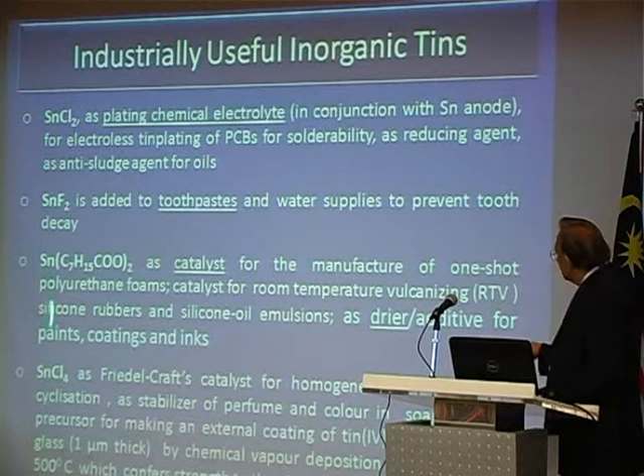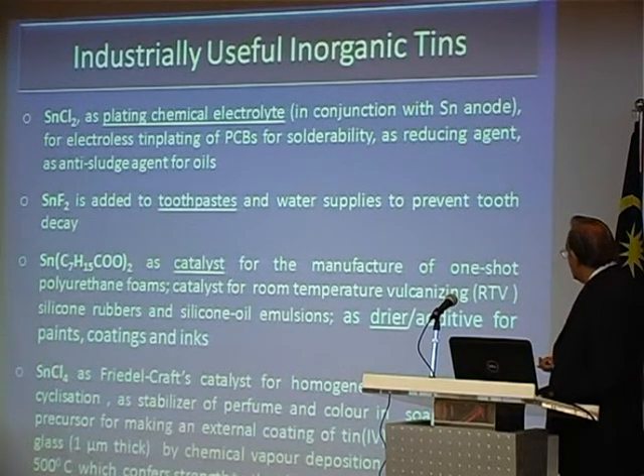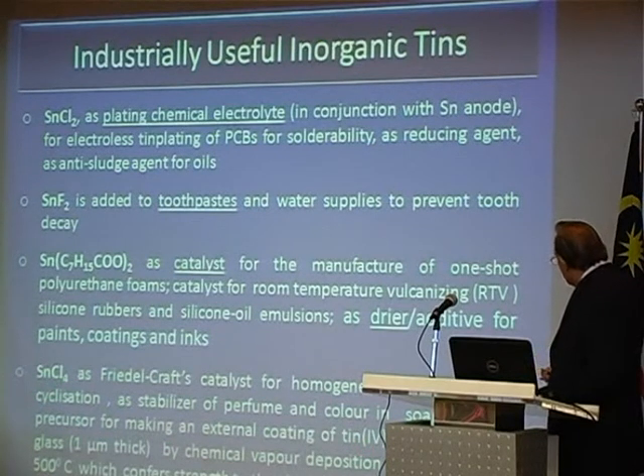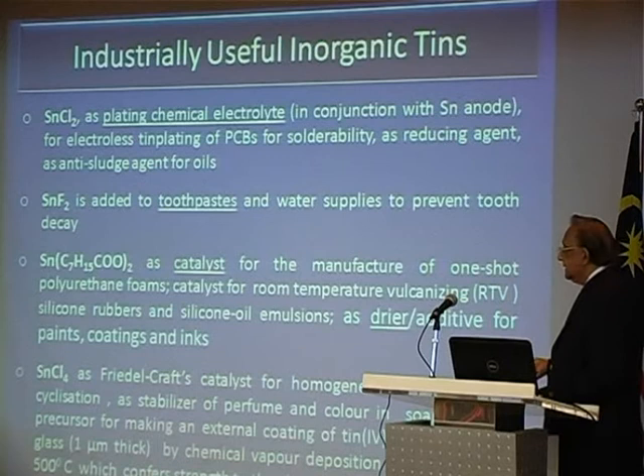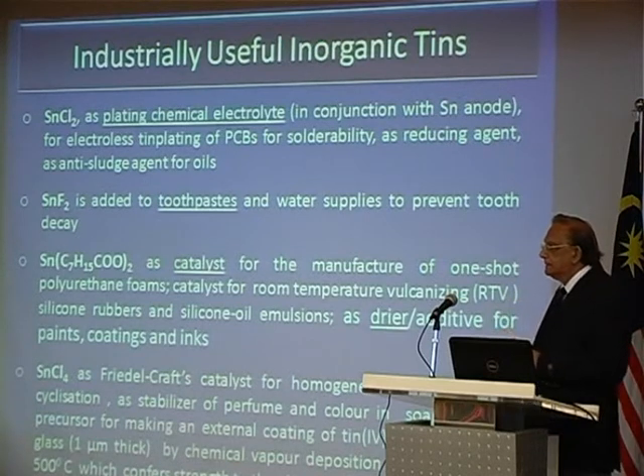Stannic chloride, tin in the valence state 4, is a catalyst for homogeneous alkylation, and, as chemists will know, cyclization. It's also a stabilizer for perfumes and color. And then, this is quite interesting. You can use stannic chloride to put a coating of tin oxide on float glass. That will strengthen the glass. You can't break it.